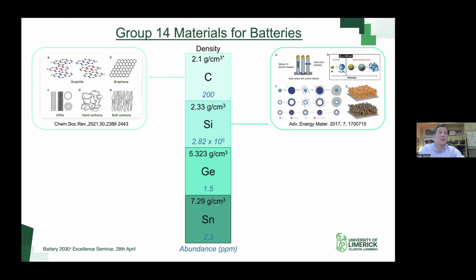Things like core shell structures, yolk shell type structures. And for example, when you go to nanosilicon with really high surface area, your SEI becomes an absolutely key issue in there. Okay, so there are significant challenges on pure silicon anodes that have not really yet been fully overcome. But the thing to say is that we shouldn't really think of these as almost silver bullet technologies. There are places for pure graphite anode materials, there are places for pure silicon, and in between.